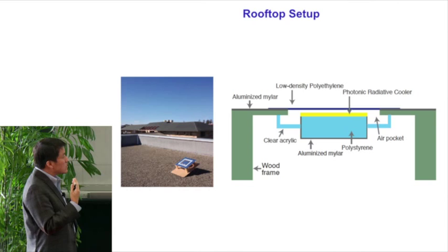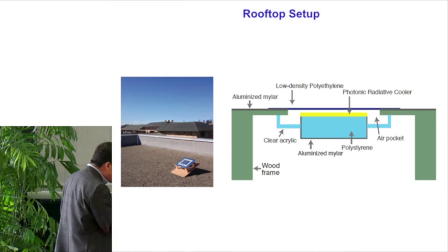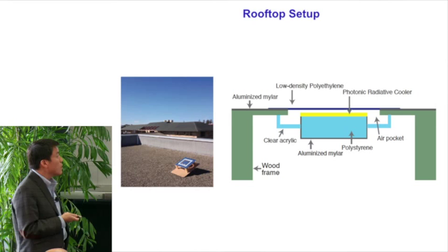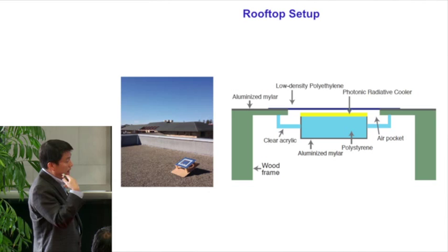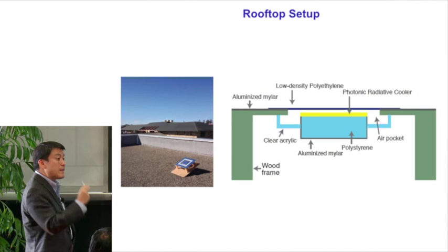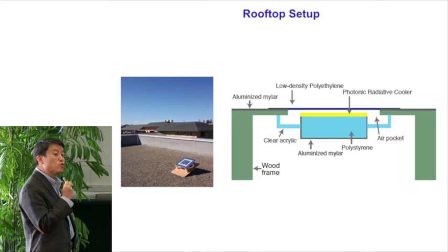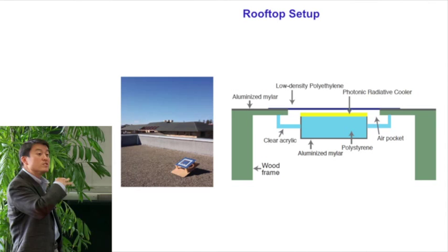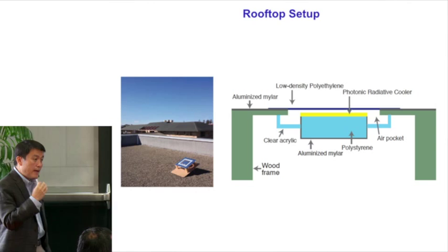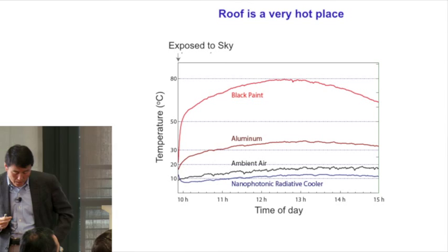And there was quite a bit of challenge in thermal design that we had to overcome in order to see the effect. So one of the key things that we eventually ended up doing is to create what we call an air pocket, a transparent box around the radiative cooler, so that nothing in direct contact with the air around the radiative cooler will be heated up by the sun. We also use a low-density polyethylene film, which is actually kitchen wrap, to seal the pocket. This cuts down the convection and, again, serves the thermal purposes. With this setup, we can then test a large number of different things under the sun.